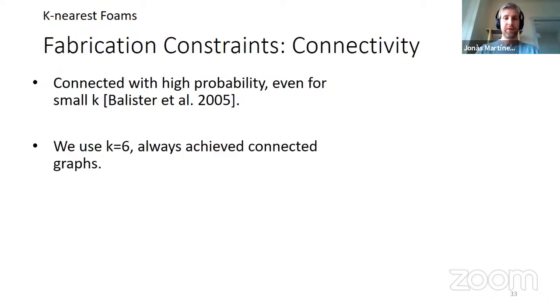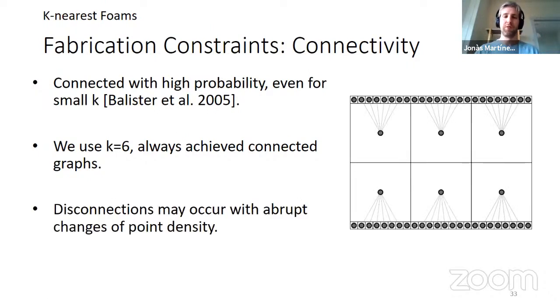That's interesting. There have been a lot of studies on what is the number k that almost guarantees that your network is connected. Because of course, if k is very small, you can have networks that are not connected. For k greater than 6 or 7, it has been proved that it's almost impossible to have a disconnected network. I could show you here a counterexample, nicely fabricated, where you get a disconnection, but this is highly unlikely, and we never encountered it.